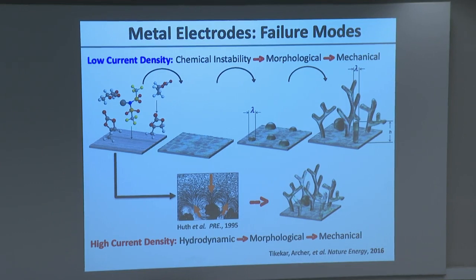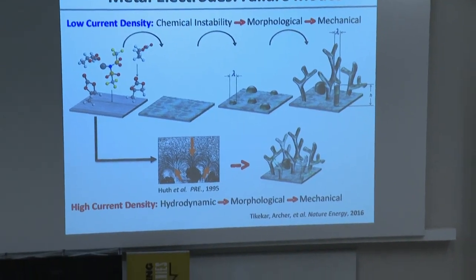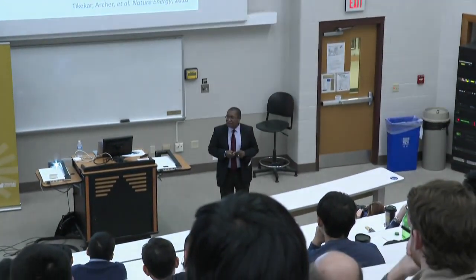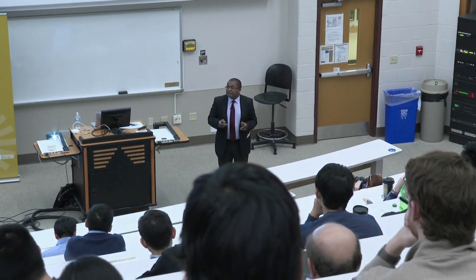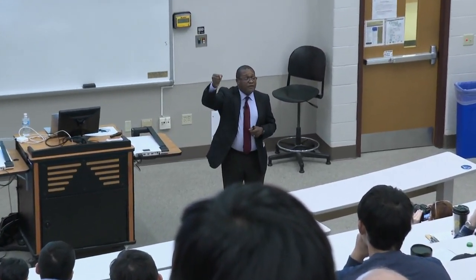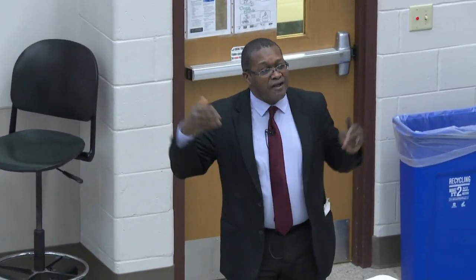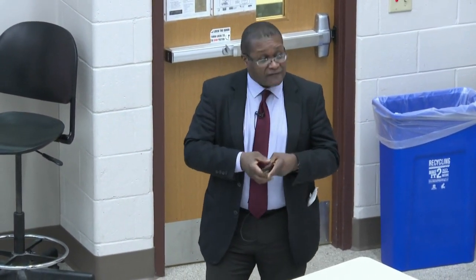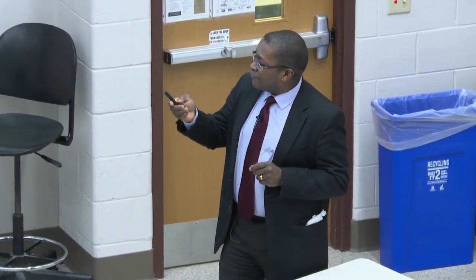Now, many of you have heard of the lightning rod effect, right? The lightning rod effect basically goes something like this, right? Your odds of being struck by lightning if you go into a thunderstorm is like 1 in 1,000,000. But if you go outside with a pointy metal pole, your odds are 1, okay? That you will be struck. And the reason for that is that the pointy metal pole concentrates electric field lines at a point, and this then makes it an attractor for the lightning strikes. Exactly the same thing occurs inside the battery, where these bumps become essentially like lightning rods. The electric field lines concentrate on the rods, accelerates the lithium deposition on the bumps, and off to the races, and the dendrites are formed.